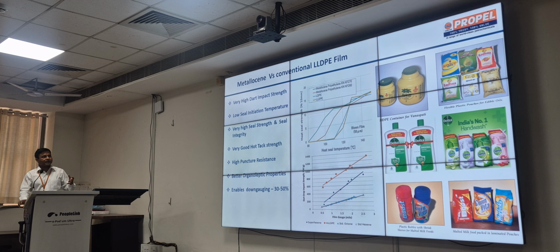If you compare with the Ziegler-Natta catalyst, the heat seal temperature, the heat seal initiation, is much lower as compared to the normal conventional LLDPE grades. And the dart impact performance, as compared to the normal 3.5 gram per micron, you are getting 25 gram per micron. So this kind of difference creates much more difference, and this is the reason why with metallocene down gauging was possible up to 50% as compared to the earlier which we have produced in the field.